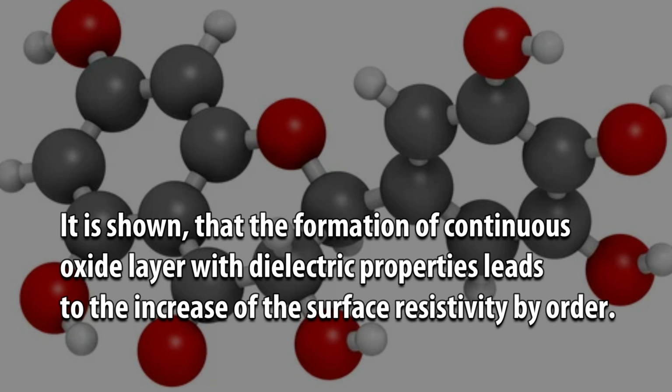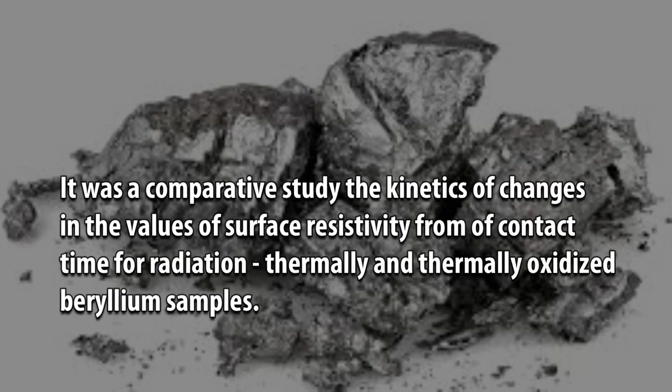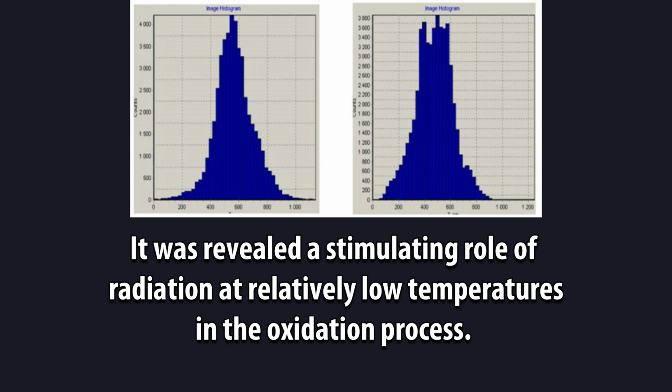surface resistivity by an order of magnitude. A comparative study was made of the kinetics of changes in the values of surface resistivity as a function of contact time for radiation-thermally and thermally oxidized beryllium samples. A stimulating role of radiation at relatively low temperatures in the oxidation process was revealed.